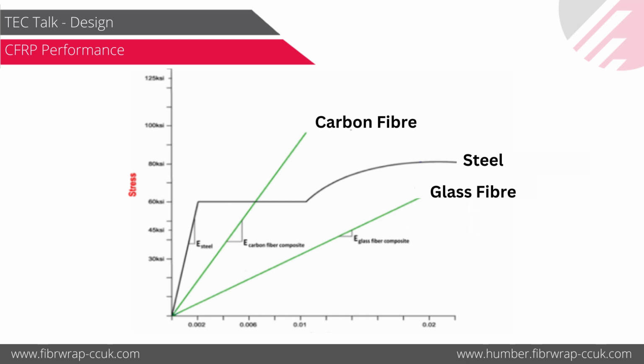But the most important thing we could see on this stress strain distribution curve is that both carbon fiber and glass fiber have a linear elastic behavior until their ultimate load or ultimate stress, which means that there is no yield point or warning in FRP before failure. So the ultimate failure in the FRP is brittle in nature. So to avoid that failure, FRP design is always a strain limit design.